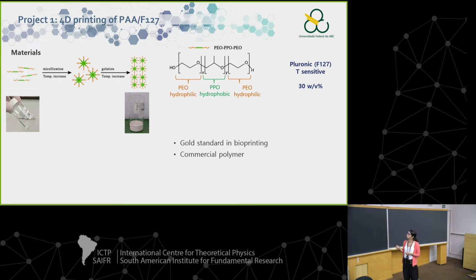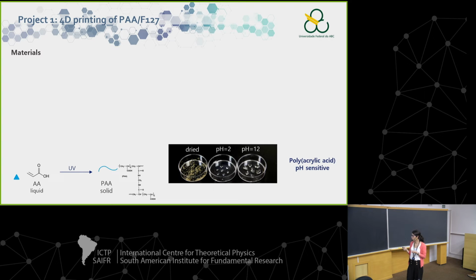At very low temperature, it is miscible in water. It forms a solution. When we increase the temperature, micelles are formed. And increasing the temperature even more, a liquid crystal is created, and so it gellifies. So we can place the gel in the syringe and then control the flow rate of Pluronic. But our goal is to develop a pH-sensitive structure.